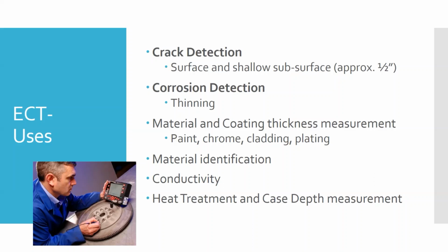So that's the other area where corrosion, that this is used in aviation heavily. Some other things that it can be used for, more on the manufacturing side: material and coating thickness measurement, things like paint, chrome plating, different claddings and stuff like that. And so it can detect paint thicknesses down to the thousandth of an inch range. So if you're trying to get a consistent paint, particularly, you can actually detect within 1,000th of an inch paint thickness differences. Different material identification, so material sorting, things like conductivity.